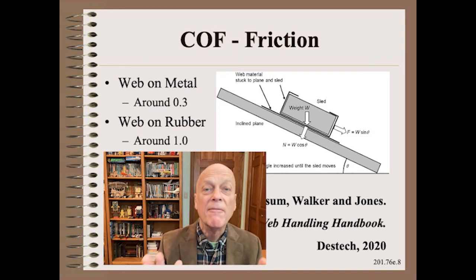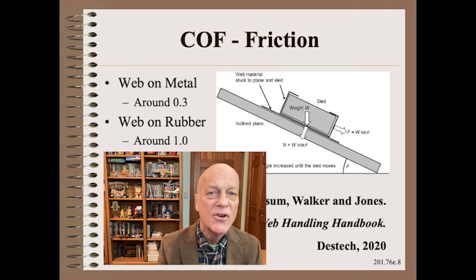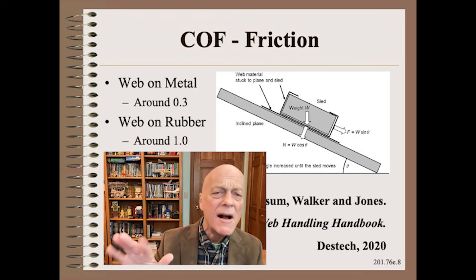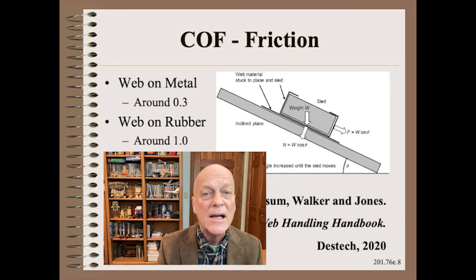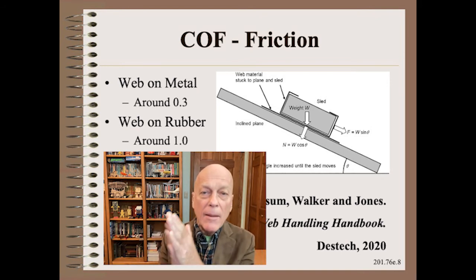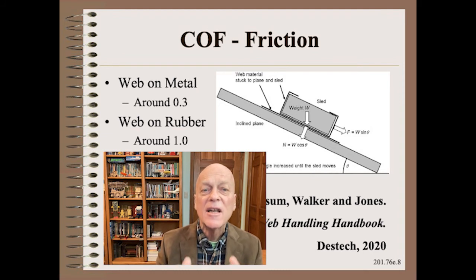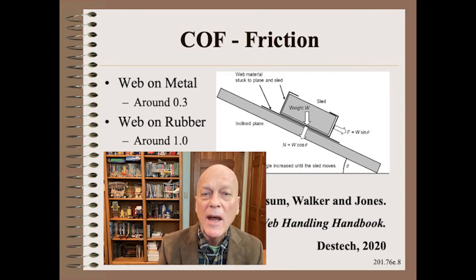I believe that friction is, by far, the most underappreciated material property in web handling. It is useful for many things, such as predicting web-to-roller traction for design purposes. The COF of most webs on metals is around 0.3, but on smooth rubber coverings can be more like 1. No less important is web-to-web COF because it informs us of what to expect for certain winding defects.